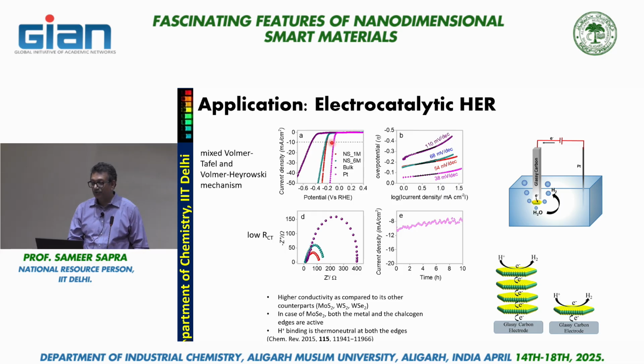And that's why you shift to some of the cheaper materials like molybdenum selenide. Okay, jokes apart, this is molybdenum selenide bulk, and that requires an overpotential of about 500 millivolts, 0.5 volts, to get minus 10, minus is just the sign convention because you're flowing electrons over there, right? 10 milliamperes per centimeter. The moment you exfoliate it